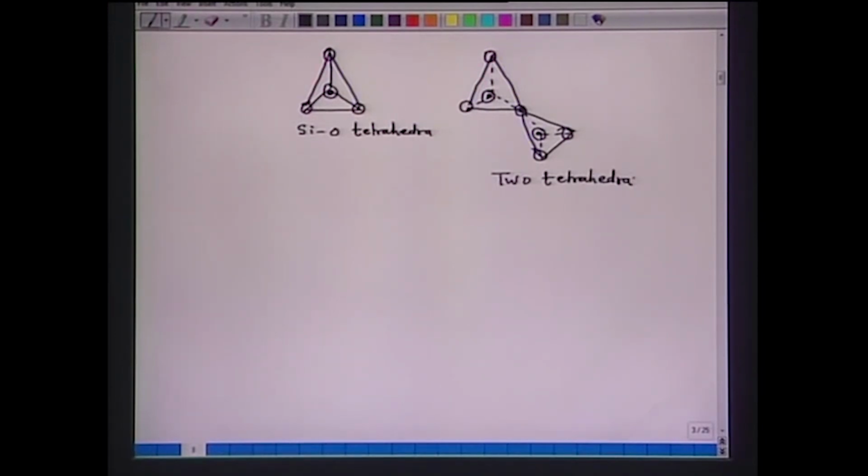What is being said here is that because cations in acidic oxides have lower radius, they follow the tetrahedral structure. That means each tetrahedron is joined at the vertex and this particular structure is repeated in 3 dimensions, and hence we get the electroneutral SiO2. So, a 3 dimensional network will look something like this.